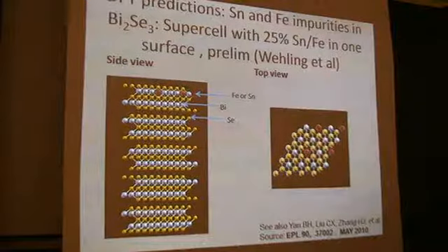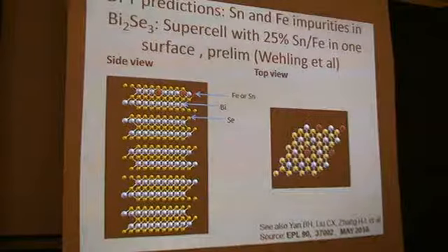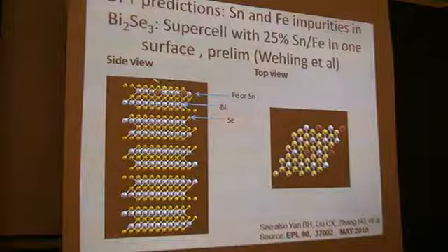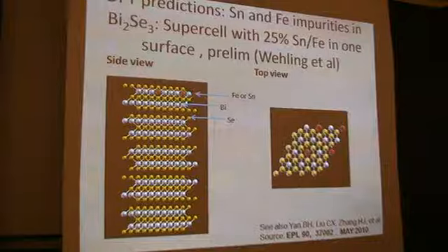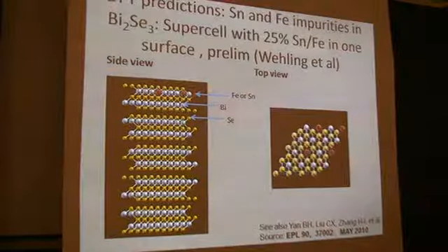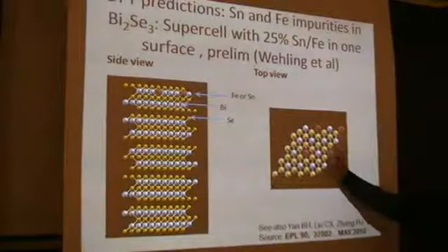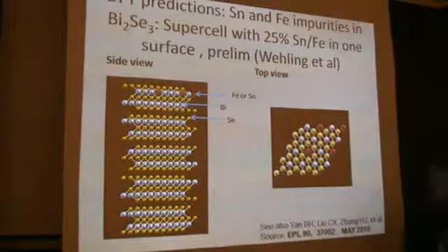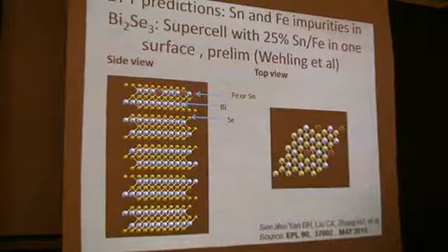But what we have is that we can look at magnetic and non-magnetic impurities deliberately placed, replacing bismuth. So here is bismuth selenide, Bi2Se3, and it's a stack of about 12 layers of bismuth, where we do the following. We go to the top layer and replace some of the sites of bismuth with either iron or tin. One of them is magnetic, one of them is non-magnetic. And then for iron, I can put the spin in the plane and out of plane. Now, the problem is that I don't have a full density of states because, as you will see, the mesh in k-space is not very good yet.